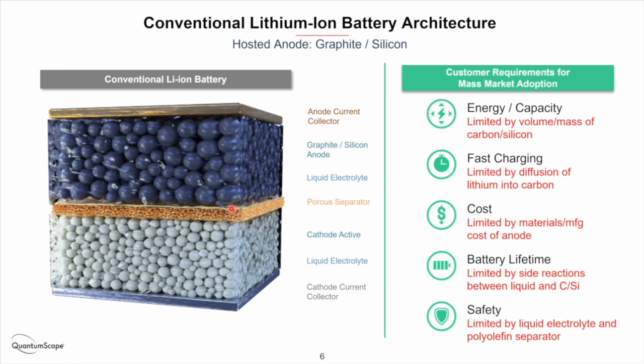In terms of fast charge, especially at low temperatures, but even at modest or room temperature, one of the limitations to be able to charge the battery quickly is the distance that lithium ions have to travel through this liquid electrolyte to get throughout the anode and then to diffuse into the graphite particles. And one of the risks in fast charge, especially as you get towards higher states of charge, is that as the graphite particles get near full, the lithium could start to plate on the outside of the graphite particle rather than intercalate inside the particle itself. And so when that lithium plates on the outside, that damages the life of the cell in a couple of ways. First of all, it'll hurt the Coulombic efficiency because some of that lithium will react with the liquid electrolyte to form the SEI layer.